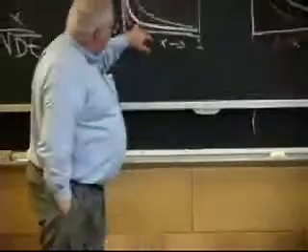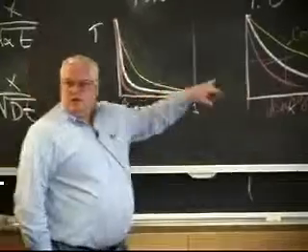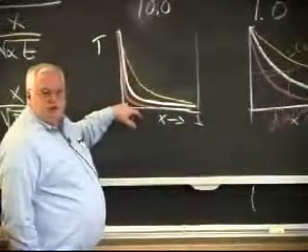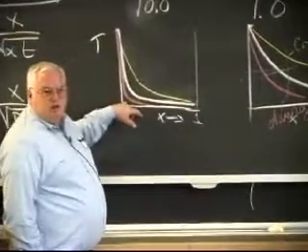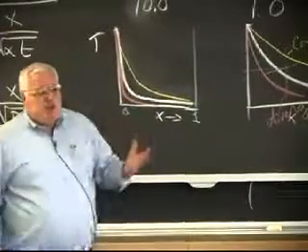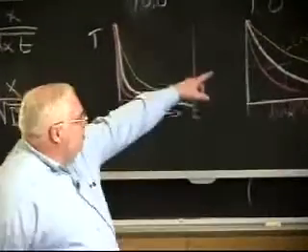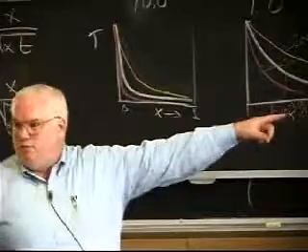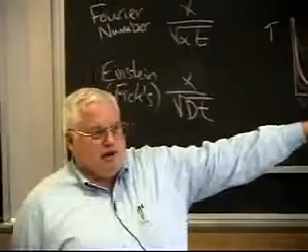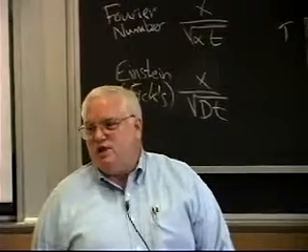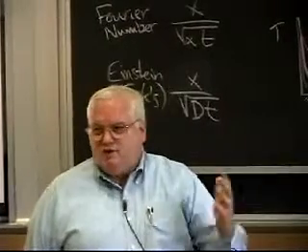So if you want to solve Bessel functions in your head, you basically say, is it thick, thin, or mixed? And is it divergent or convergent? And it's going to be on one side or the other of this, with about a 10% difference. Do I care about 10%? I probably don't know the thermal diffusivity within 10% for most of my materials. So who cares? So in what cases does it apply? Basically, it applies in all cases.